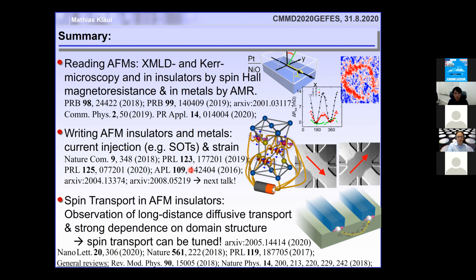Yeah, so that's an extremely valid point. This is where we did all these studies on the temperature dependence when we go up to the Néel temperature. But at least from our experience, it looked like the systems, when they approach the Néel temperature, we simply lose contrast before there are some fluctuations that might increase the number of domains. So I think that very close to the Néel temperature might play a role. But at least from what we see, down to the temperatures where we see good contrast, the intrinsic pinning of the domains is stronger than the thermal fluctuations.